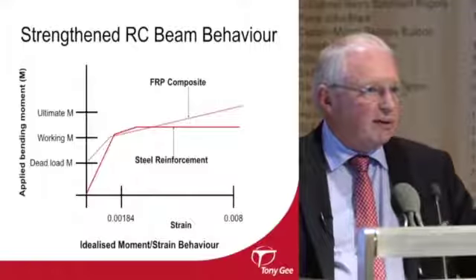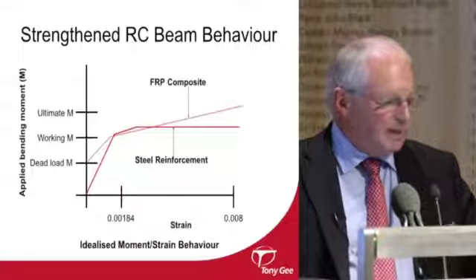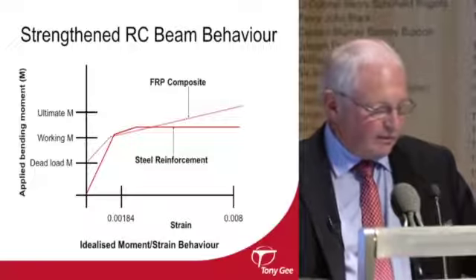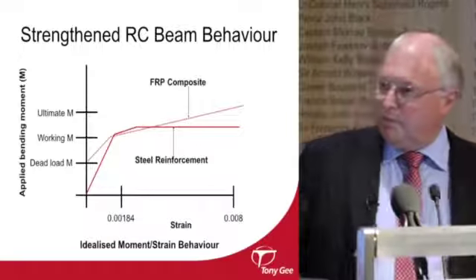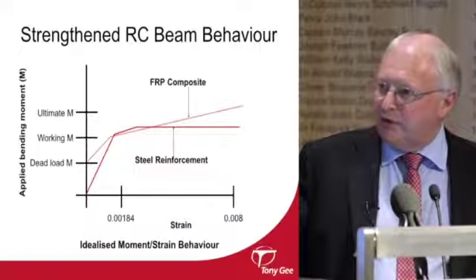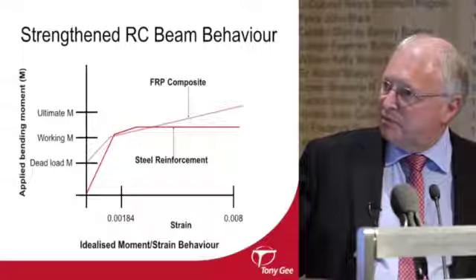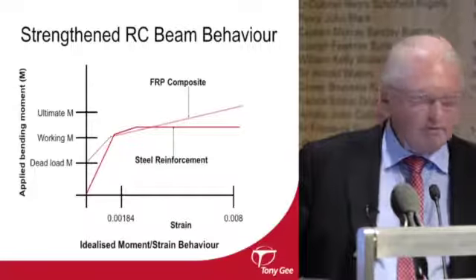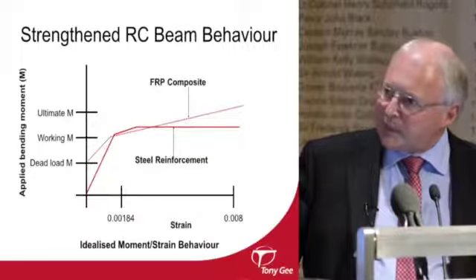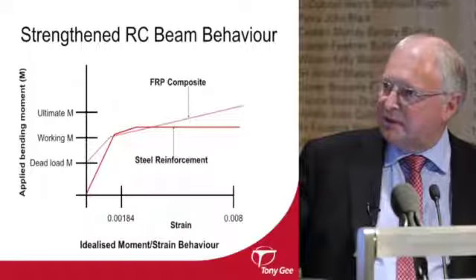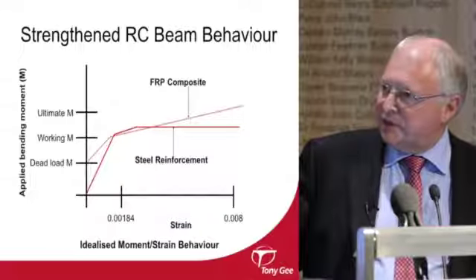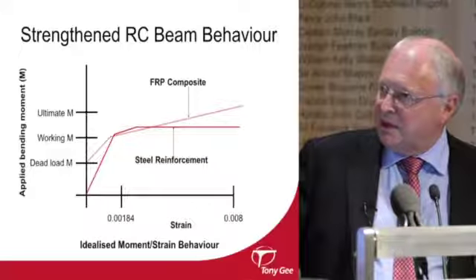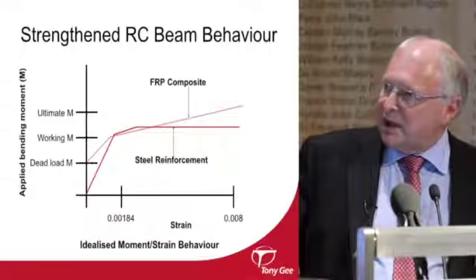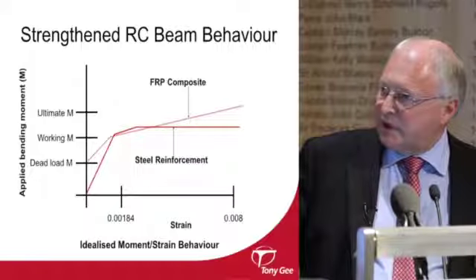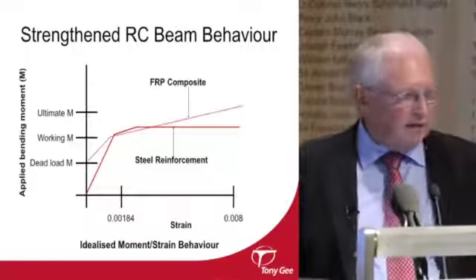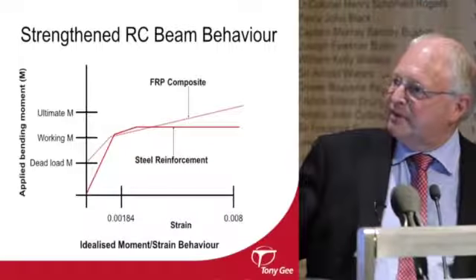So if you just draw a bit of a graph to try and demonstrate what's doing the work at any point in the loading cycle. This is obviously a flexural strengthening scheme. In most cases, we're probably not going to remove dead load, or not very much of it. So when you put your FRP composite on, it doesn't have any stress in it at all, or any strain. And then as you apply your load and increase the bending moment, the steel reinforcement is starting to strain more, and the composite is starting to strain more. And they're both working together until this point, at which point the steel reinforcement says, I've had enough, I can't do any more. You're on your own, FRP.